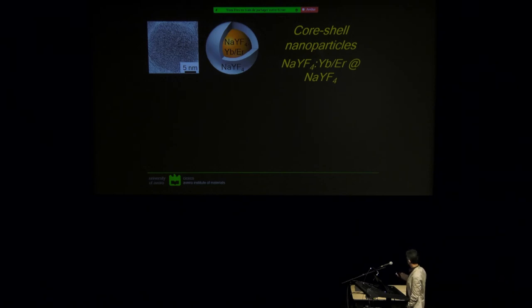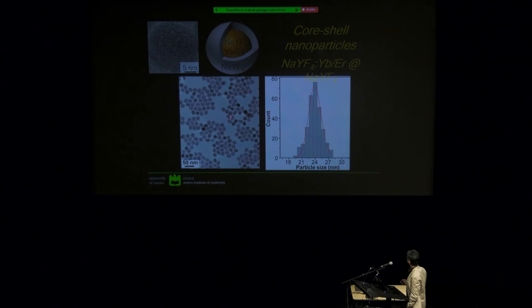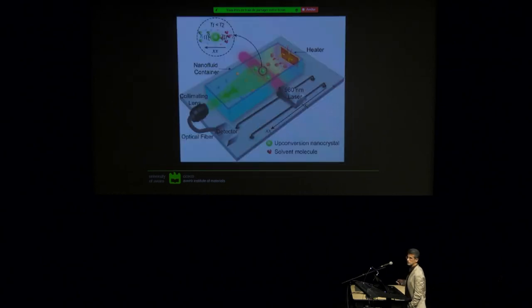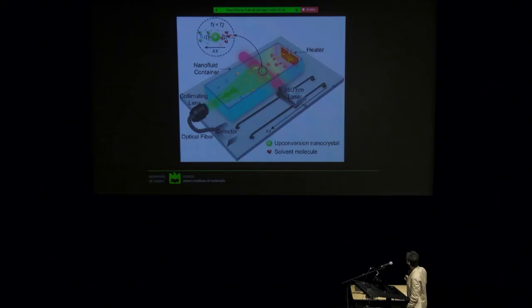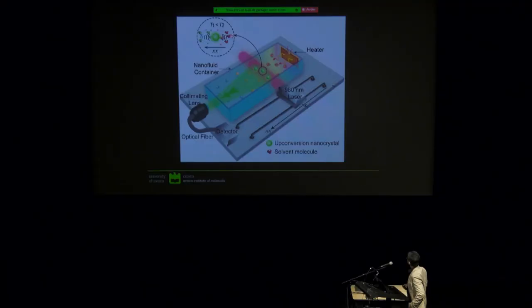And with these particles, by the way, we have almost monodispersed particles, so quite a narrow distribution, around 24 nanometers or so. So using these nanoparticles, we did the following experiment, and I'll try to explain this in a very, very simple way. So we had a cuvette, and inside this cuvette we had water sprinkled with our nanocrystals. So they were here. They were swimming in this pool. And we had a heater here.